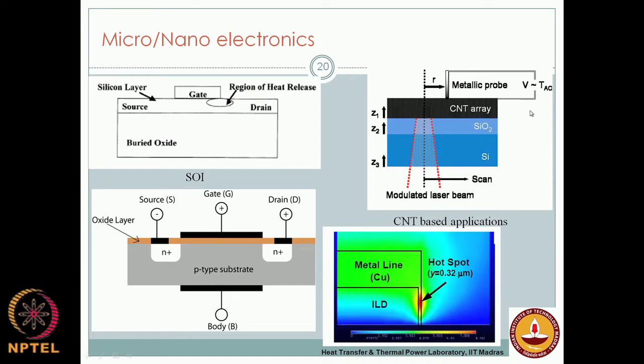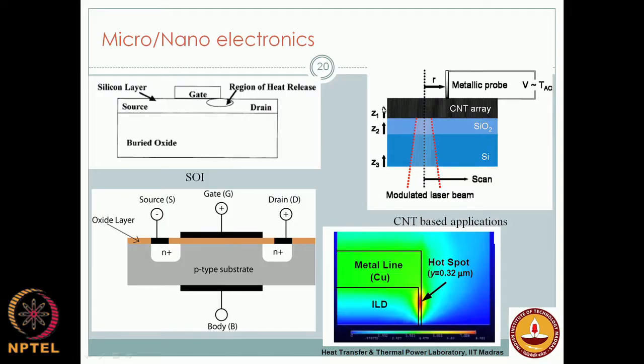Similarly, people have been trying out a lot of novel materials where you can improve the thermal conductivity in a certain direction. This can be achieved by using what we call carbon nanotube arrays. Over the last decade or so, carbon nanotubes have emerged as very promising materials for microelectronics, because you can tune their electrical and thermal conductivities in certain directions to be enormously high, and they can be grown vertically on substrates like silicon dioxide. You can use them as thermal interface materials, and thereby reduce the interfacial thermal resistance and the size of these hotspots.